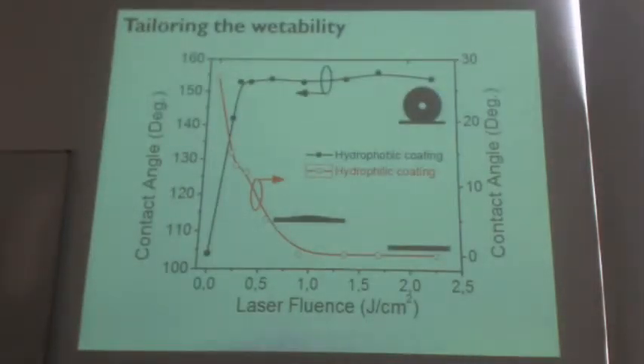And this is the effect of chemistry now. If one has a hydrophobic coating on the top of these surfaces, you can tune, using the different parameters, the wettability from a hydrophobic to a super hydrophobic state. You can see it here. However, if you have a hydrophilic coating, then one can switch from a hydrophilic state to a super hydrophilic state. So in this case, the surface is completely wettable.